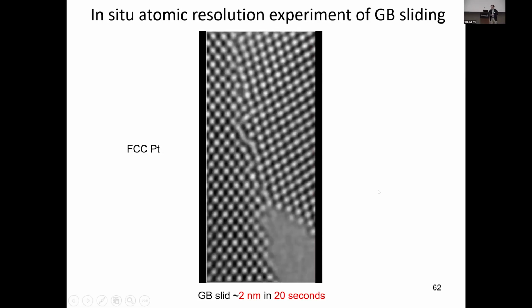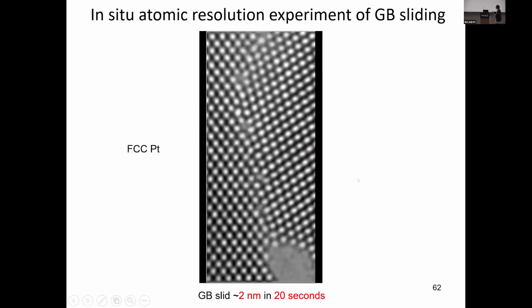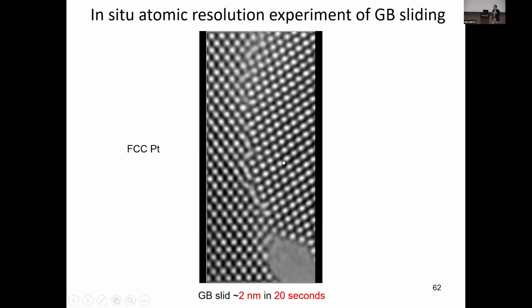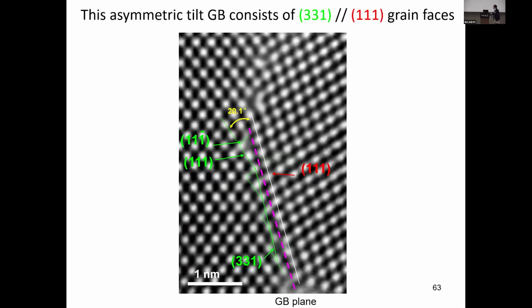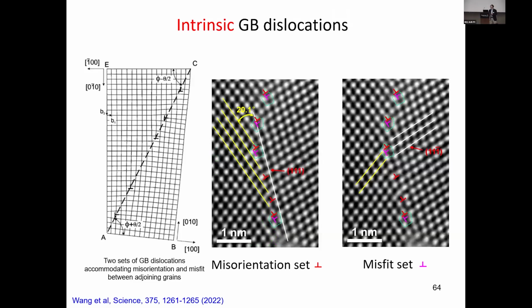In this short video, which lasts about 20 seconds, you can see the sliding displacement is about 2 nanometers. The atomic spacing is about 0.2 nanometer, right? So the sliding occurs across 10 atoms. So this is a particular asymmetric grain boundary. Even with just a short video and a small segment of experiment, we can learn quite a bit of new physics and also obtain new understanding of the atomic-scale deformation process.